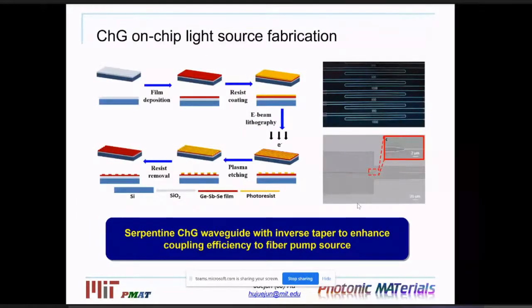Now, the next step is that we want to integrate this light source efficiently with on-chip waveguides. On the left-hand side, I'm showing the fabrication process of the chalcogenide on-chip waveguides. We use standard lithographic patterning coupled with plasma etching to create these waveguide structures. We also shape the waveguides, in this case, into a zigzag structure to enhance the interaction length while at the same time preserving a small on-chip footprint. One more feature I want to mention is that at the end facet of the waveguides, we also create inverse tapers of the chalcogenide waveguides along with a polymer taper made of SU-8 epoxy. With these end facet couplers, we were able to significantly reduce the coupling loss from the fiber laser onto on-chip waveguides, which is beneficial to enhance any kind of nonlinear interactions.